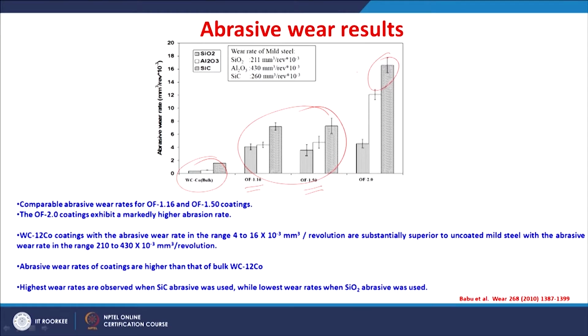With respect to the abrasive used, the silicon carbide abrasive always gave a higher abrasion wear rate, whereas the silicon oxide abrasive always gave a lower abrasion rate. In addition to that, one important point is that for tungsten carbide cobalt coatings, the abrasive wear rate is in the range of 4 to 16 × 10^-3 mm³ per revolution, which is substantially superior to the uncoated mild steel with abrasive wear rate in the range of 210 to 430 × 10^-3 mm³